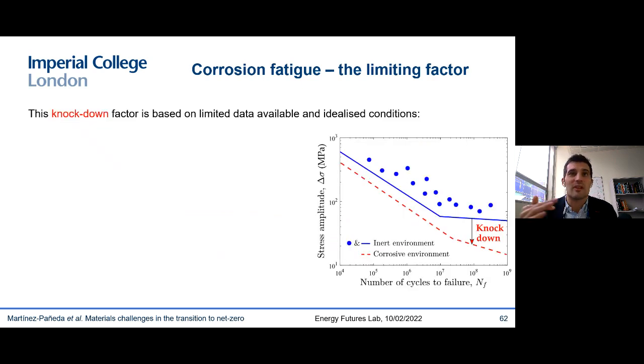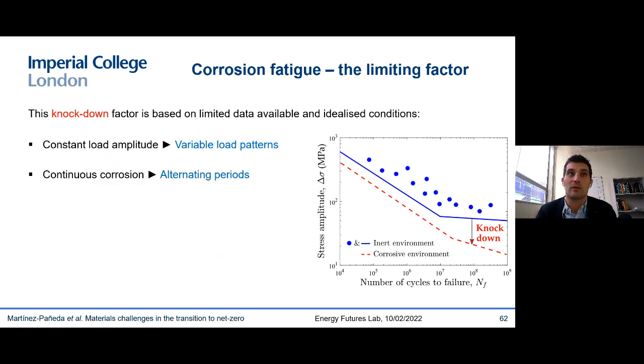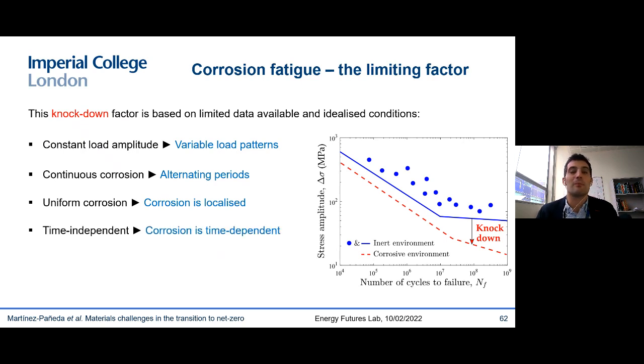And I think it might sound to you a bit arbitrary, but also the entire protocol is based on a number of assumptions. For example, we consider that the load amplitude is constant, but in reality we have variable loading patterns. We also assume that corrosion is taking place at all times, but in reality we alternate periods of protection and periods of corrosion. The wind turbines are not exposed to corroded environments all the time, they're protected. We also assume that we have uniform corrosion, but corrosion is often localized, so you have pitting and localized corrosion. Of course, time doesn't come into play here. However, corrosion is a time-dependent phenomenon. And also we're using smooth samples, very simple cylindrical samples, but real structures have complex geometry, so you could think of a weld, for example.